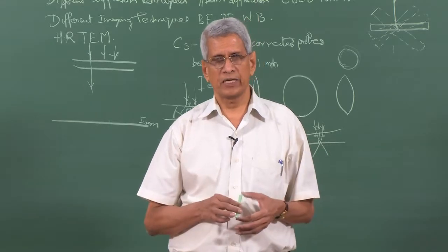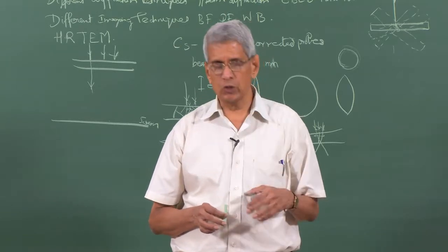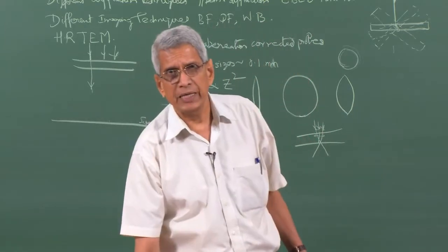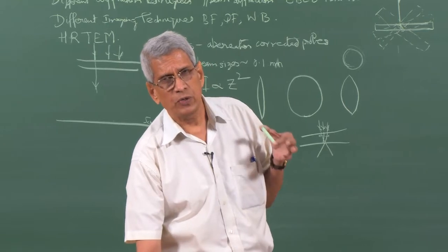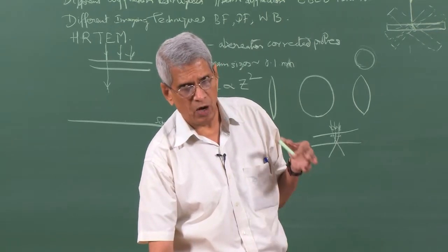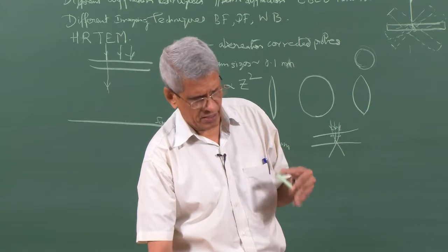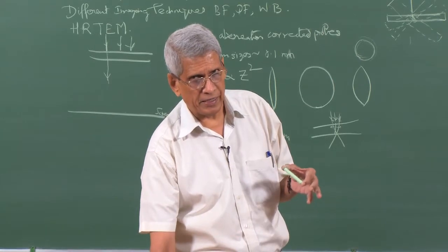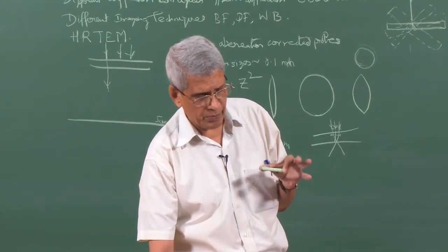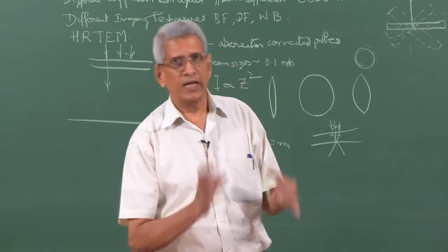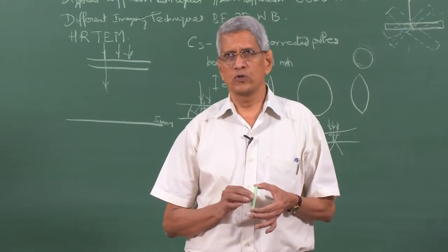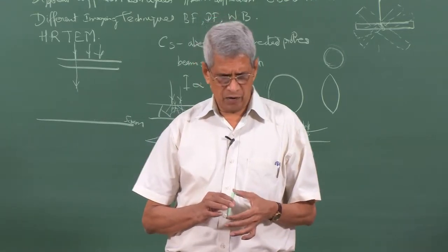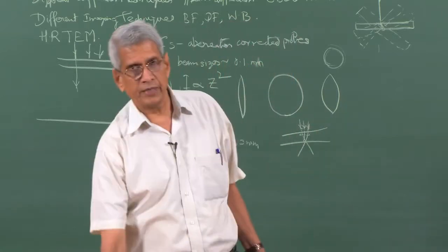Similarly, suppose we take a thin film superconducting magnet, we wanted to know how the field lines penetrate through that sample as we change the temperature. All these experiments we could do, and get information about how much of the magnetic induction is passing through, penetrating the superconducting sample. This information could be obtained using this technique. That is, we can directly image and also quantify it. This is one of the greatest advantages of using electron holography.